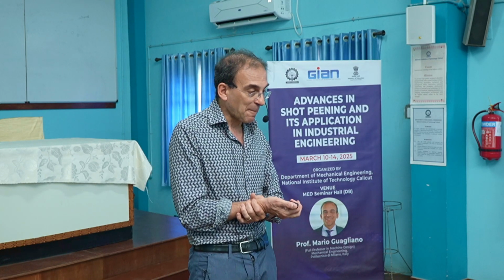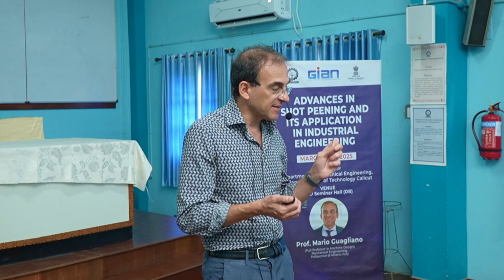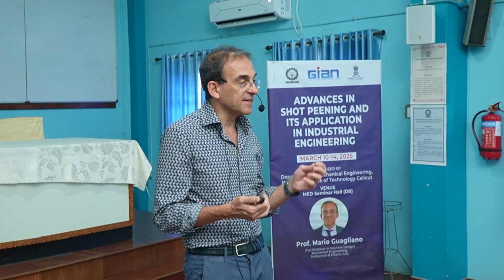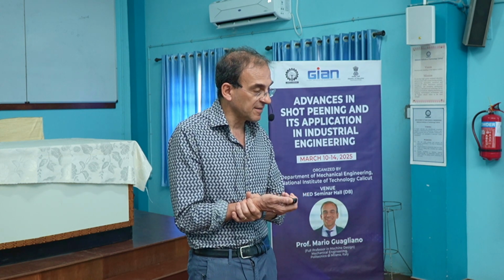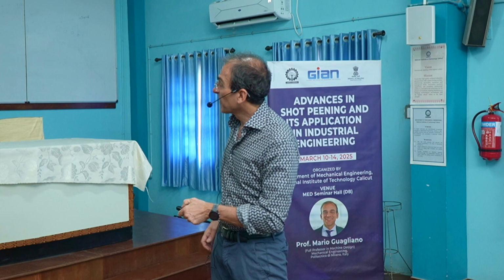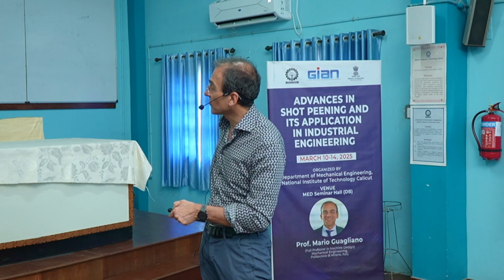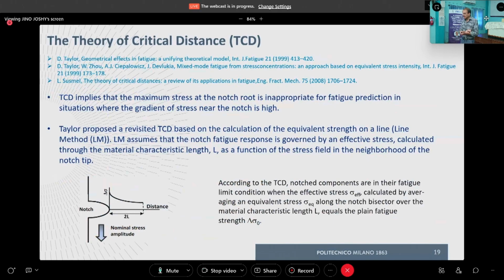Taylor proposed that the parameter used for estimating the severity of the fatigue load, let's say the stress that can induce fatigue, should consider a finite distance from the surface, here called 2L, and we should consider the trend of the stress along this line. The parameter we use is the integral of this trend, averaged over the length. This characteristic length is a material characteristic, and one that also depends on the geometry according to the notch tip geometry.